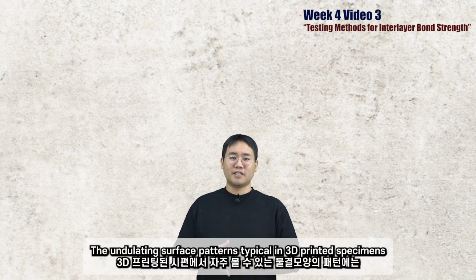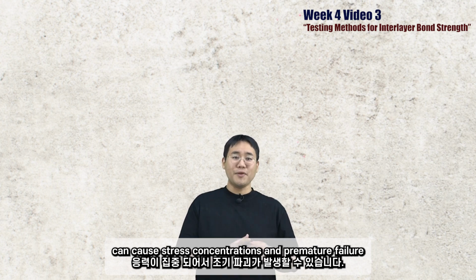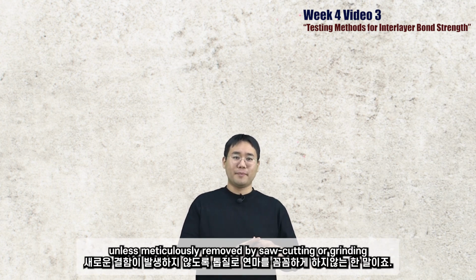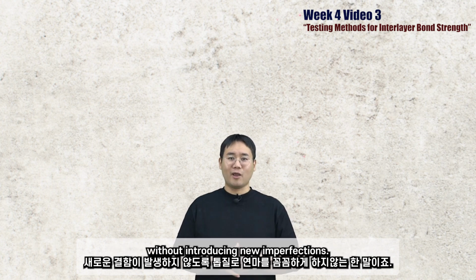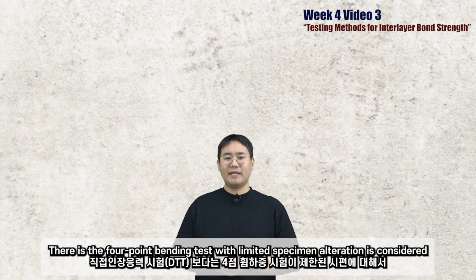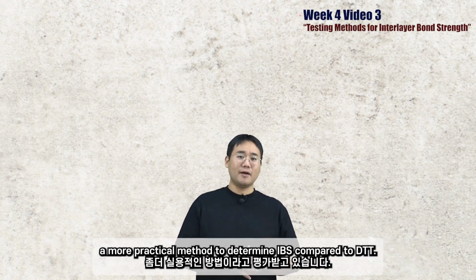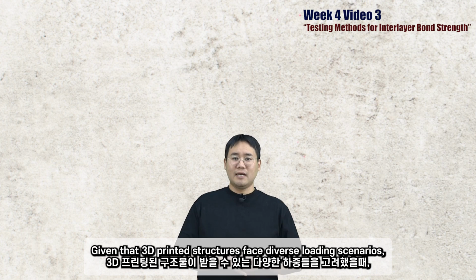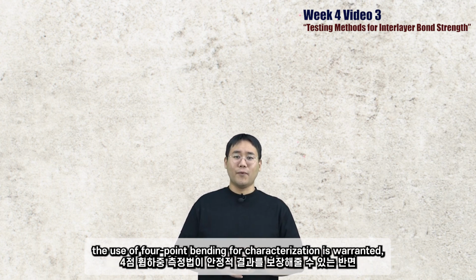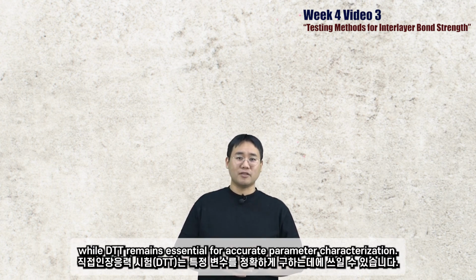The undulating surface patterns typical in 3D printed specimens can cause stress concentration and premature failure unless meticulously removed by saw cutting or grinding without introducing new imperfections. The 4-point bending test, where limited specimen alteration is needed, is considered a more practical method to determine IBS compared to direct tensile tests. Given that 3D printed structures face diverse loading scenarios, the use of 4-point bending for characterization is warranted, while direct tensile tests remain essential for accurate parameter characterization.